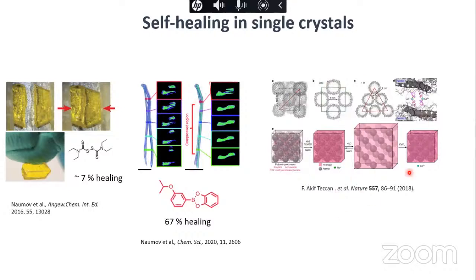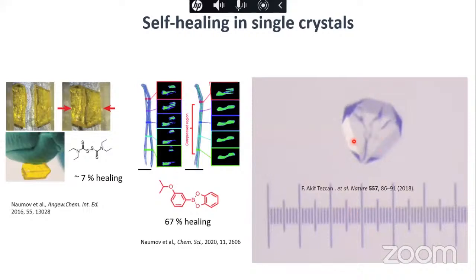And this is another example where you have a protein and polymer hybrid, a gel polymer basically. When you put this crystal in solution, it swells. Again, you take it and put it in a buffer with a different concentration, and then it shrinks. In this process, it develops cracks, and then slowly the cracks disappear again on their own. So this is also one example. But this entire process happens inside the solution, and the cracks are also not mechanically generated. They are generated when the crystal swells.